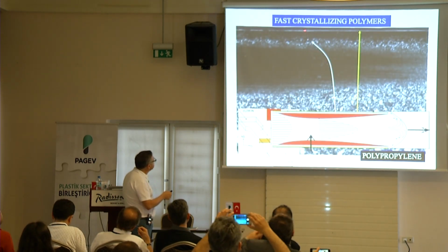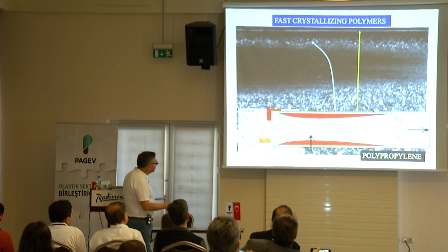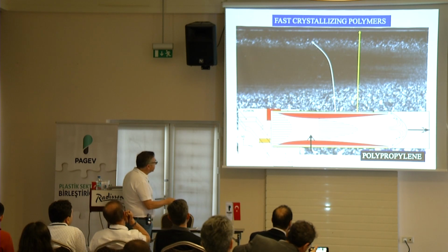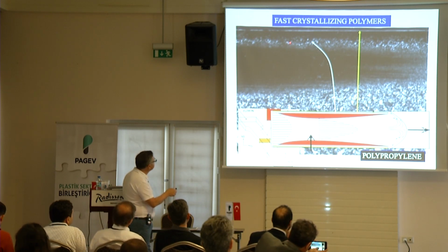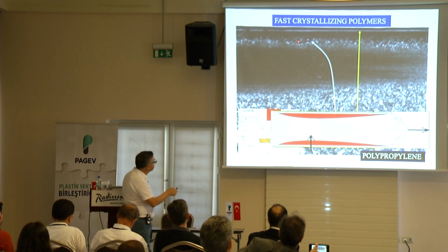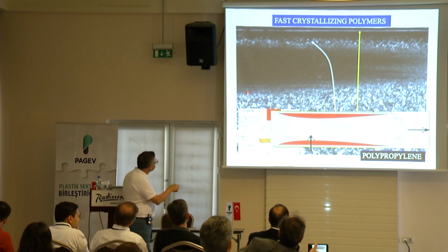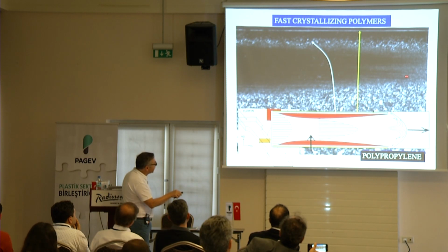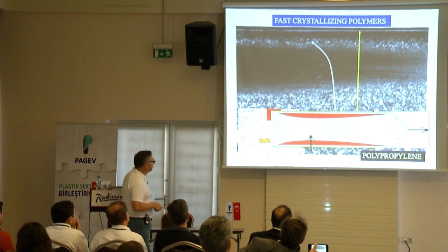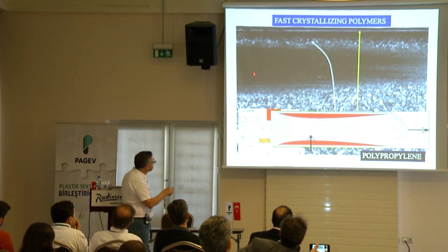You see, this is the skin. This very skin is basically the yellow portion that formed by the biaxial stretching right there. And in between, interestingly, your nucleation rate goes down. So even though it's close to the skin, the size of the crystals is a little bit larger. And then you have this red region representing this dark region. You see? What's interesting is that if you look at the edges, it's not necessarily homogeneous. There are some threads forming, like shish kebabs and so on. Those are formations on the edge. So in this particular case, when you have shear domination, the extensional component domination, the size of the crystals becomes so small, this is what you get.